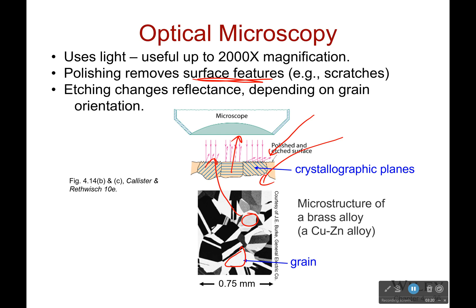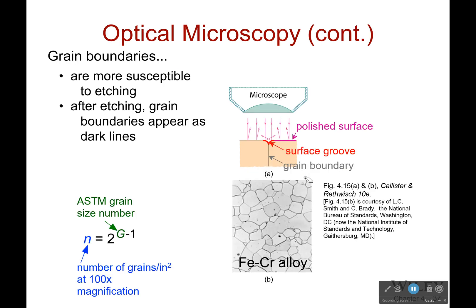So this is one way we can figure out the different grain structures inside a material. Now, grain boundaries are also quite susceptible to etching, and after we've etched the surface, a grain boundary is going to appear as a dark line. The reason they are susceptible is that at the edges of grains it's weaker — we have all those defects there.